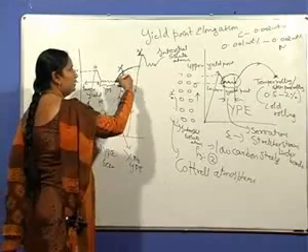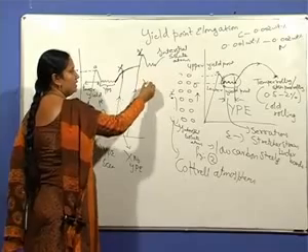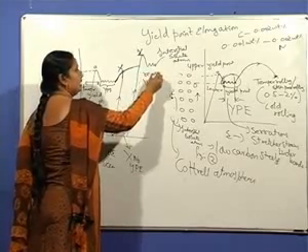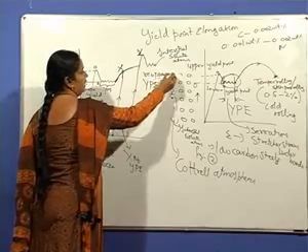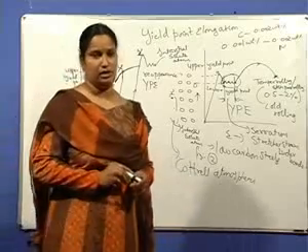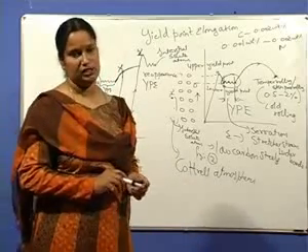Thereby the yield point elongation reappears, but at a greater stress than before. This is known as static strain aging.